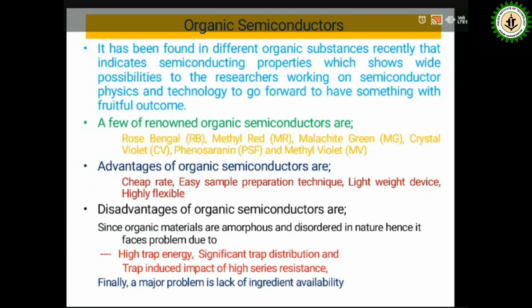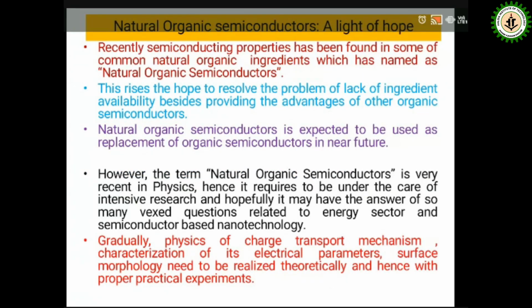So the material bulk resistance is high, as well as it has a high trap energy. High trap energy means the charge comes and gets trapped in some voids. So we will not get the power in the output, and efficiency will be low. So there are high energy traps, significant trap distributions, and the trap induced impacts of high series resistance. Finally, a major problem is the lack of ingredients available. Pure materials for laboratory purposes are a problem, although we know they are not very much available.